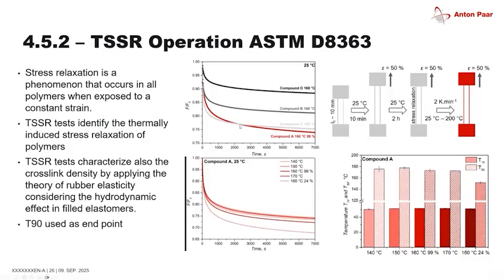There's a beautiful application note from our rheology team from Anton Paar. I'm glad to forward this to you guys if you're interested. It shows you the stress relaxation once a material is exposed to a constant strain and the temperature changes. So you have the strain, then you hold it for a specific time, and then you do the temperature ramp and see how much it changes until it rips. There are a couple of abort criteria, but normally you have the 90% crosslink as an endpoint. And again, the ASTM standard would be D8363.